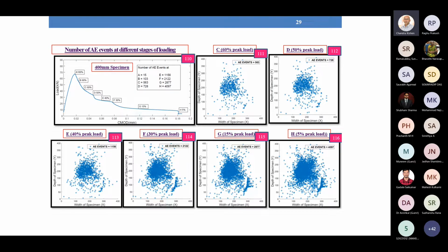We are performing this direct tension test, and after the direct tension test, we'll be doing fatigue tests in direct tension, in compression, and in a combination of tension and compression. This is basically to get a complete failure envelope for concrete. In all the finite element models today, the failure criteria used are based on experiments done on very small, lab-size specimens, basically cubes of 150 millimeter, so very small specimens.